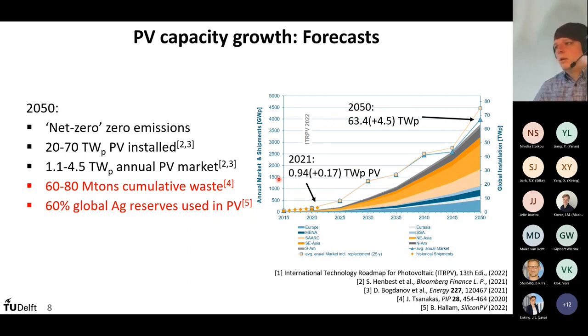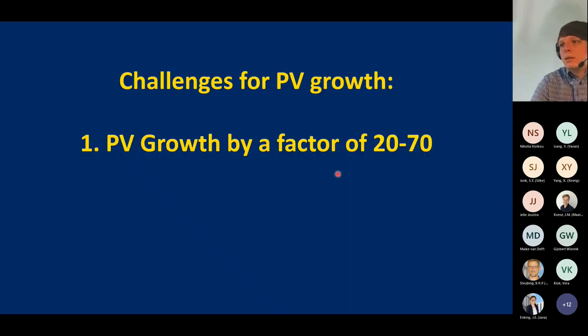So already today, for 200 gigawatts or 0.2 terawatt, we used 10% of the annual silver supply. So in terms of silver, we will really hit a wall pretty soon. So the key lesson is that we need to fulfill the Paris Climate Agreement. We will need PV growth by a factor of 20 to 70.